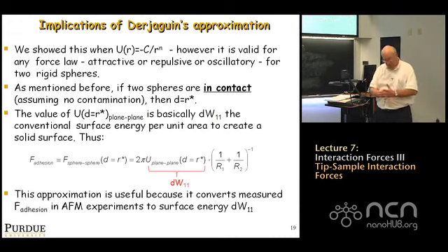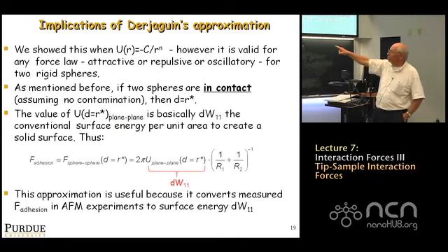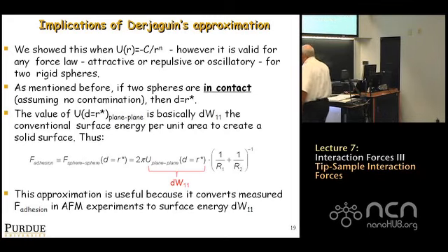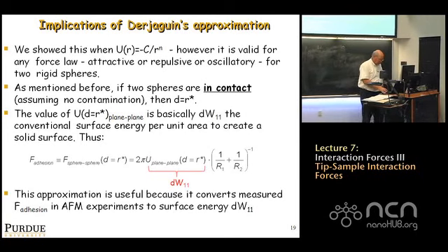work to produce a surface, this dW11. That's that plane-plane interaction energy. That's this surface energy, dW11, that we talked about earlier. That's a fundamental quantity. So if you can ever achieve experimental conditions where you can make an accurate and reliable measurement of the separation force between a sphere and a plane, in principle, your measurements can be used to infer these fundamental surface energies. So that's why we mention it, but I think it's hard experimentally to pull off.